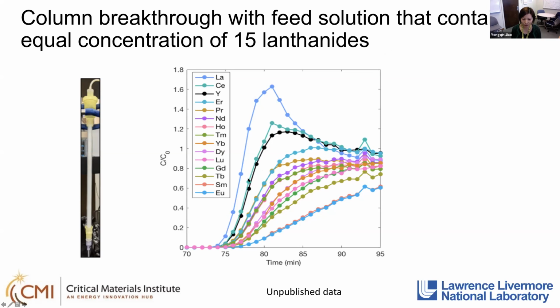So this is what the breakthrough curve looks like. As you can see, again, consistent with the electronic waste leachate, all of the rare earths' breakthrough points are very similar. And towards this direction of my mouse, the curves show the order from the lower affinity of the lanthanide binding tags to rare earths towards higher affinity. And this slope is consistent with what we observed in terms of lanthanide binding tag rare earth complexation affinity that we previously observed in solution phase.